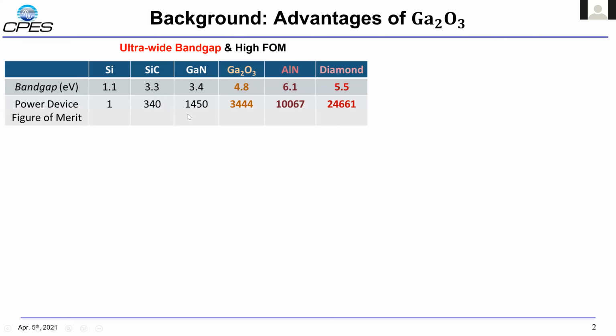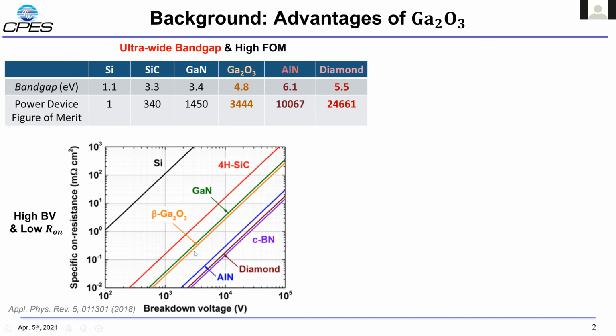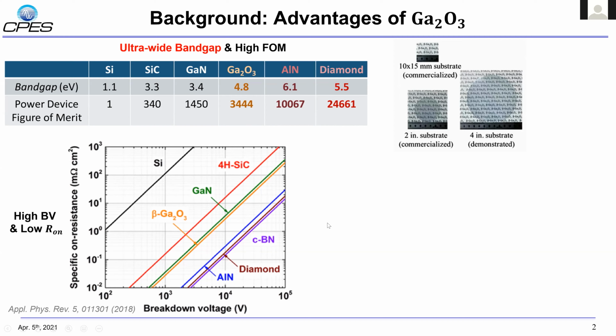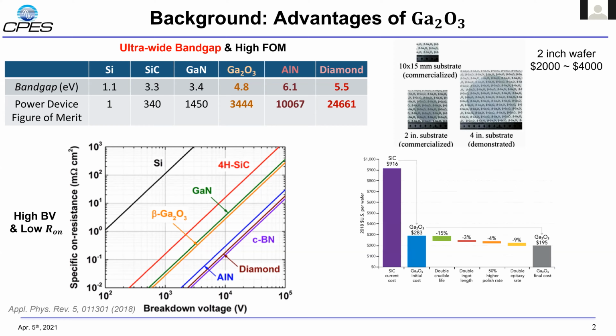First, let's talk about the advantages of gallium oxide. Gallium oxide is a semiconductor material with ultra-wide bandgap, and therefore it has higher power device figure of merit compared to silicon carbide and gallium nitride, which means that, potentially speaking, it can have lower on resistance at the same breakdown voltage level. Although the commercial gallium oxide wafer is expensive for now, in the future, in large-scale industry manufacturing, they can be much cheaper than gallium nitride and silicon carbide substrate because of the melt-based crystal growth process.